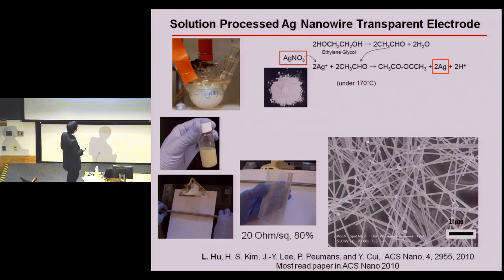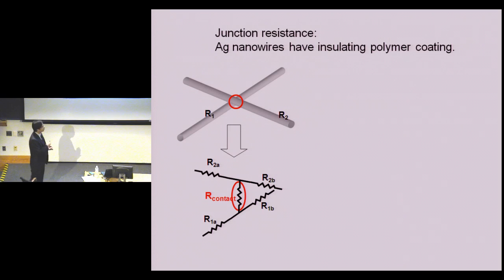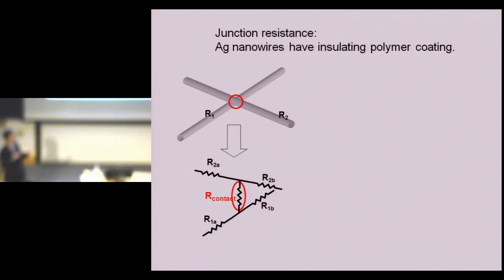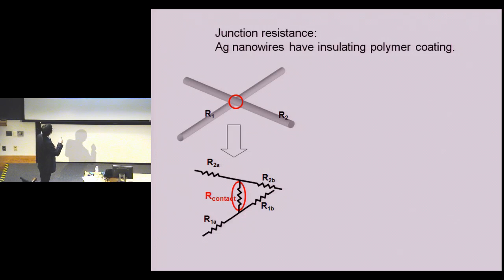And if you look into the detail here, it's a random network made of silver nanowires. And of course, these silver nanowires are highly conductive to electrons. But meanwhile, you will have a junction resistance between the two different wires. So this junction resistance will decrease the performance in terms of sheet conductance. The reason is that we have a polymer coating on the surface of these silver nanowires, and these polymers are insulating in nature. That will cause large resistance for the electron transport from one wire to the other.